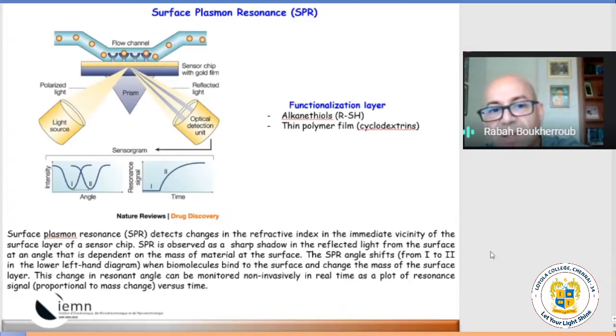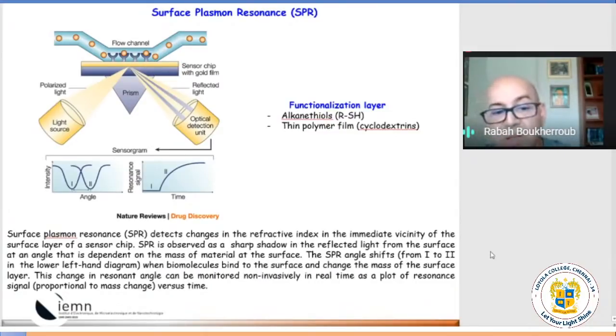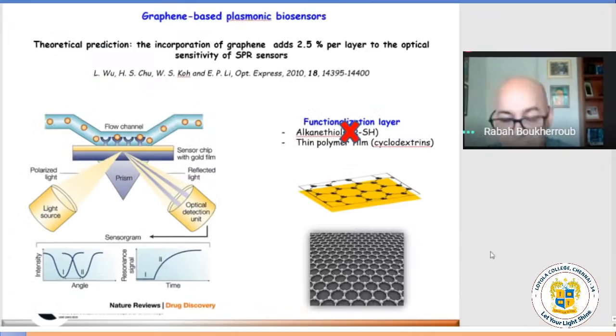Now, if I change the refractive index on the gold layer, it means I can put biomolecules on it, or chemicals, or polymers, whatever you want. You change the refractive index, you change the mass, and this minimum shifts. And when it shifts, that's exactly the amount of material you have on the surface. So you can detect the change of refractive index mostly, which is indirectly connected to the mass change on the surface. Normally, you have to functionalize the sensor to make it selective and sensitive. So typically you buy these slides, so they have a thin polymer film with cyclodextrins, or you put what you call an alkanethiol functionalization layer on the gold surface.